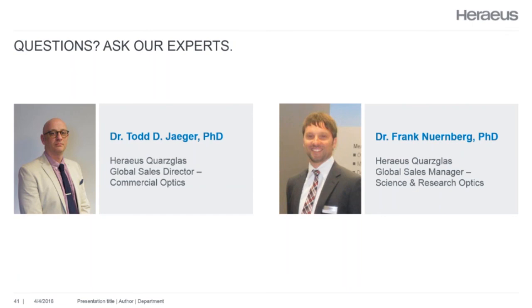Okay, thank you very much. And here's our next question. Is there any correlation between homogeneity and birefringence? So what we have seen in our material is, in the early stages of the production chain, if we try to measure the optical homogeneity, it's not possible to measure it due to the fact that the stress in the material is too high to resolve that. After our annealing steps, we are able to measure the optical homogeneity.